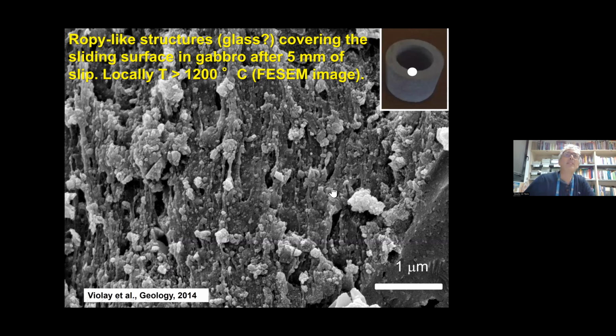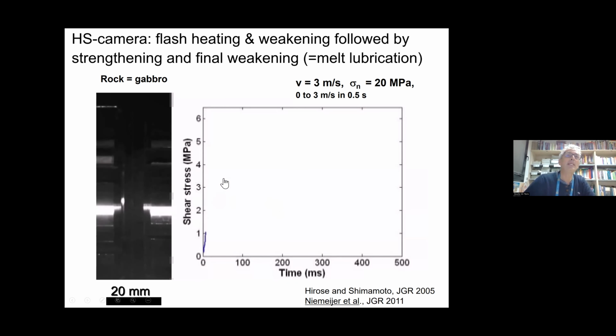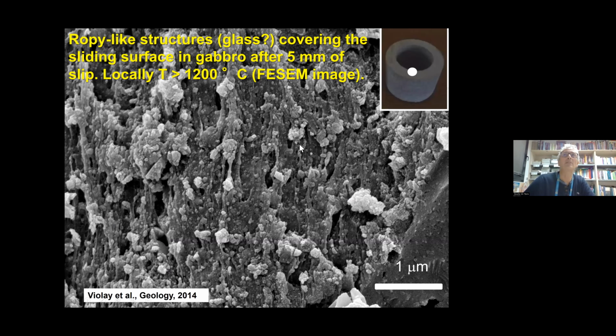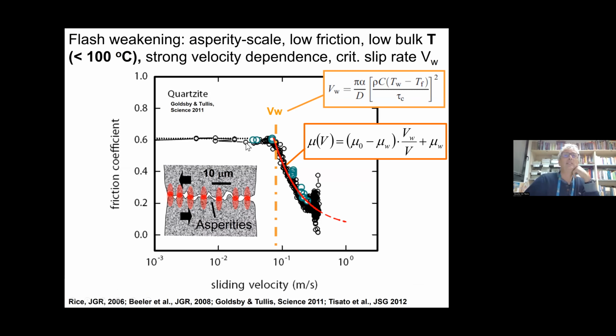But this is what you see if you stop the experiment at the beginning. If you stop the experiment after 1 millimeter of slip or a few millimeters, like in this experiment, you can find at this scale, this is a 1 micron bar, these patches of solidified glass. They are evenly distributed. There are some here, others there. They're not continuous. And this goes to this mechanism, flash heating and weakening. This happens probably in every earthquake, even magnitude 0, very small. You need a very small slip distance to have this.